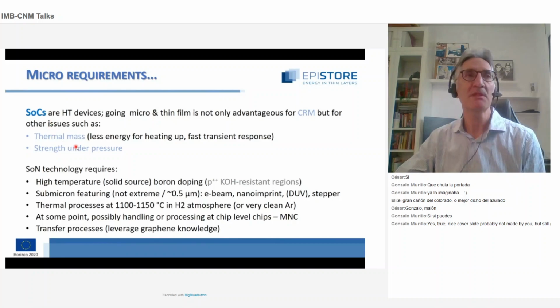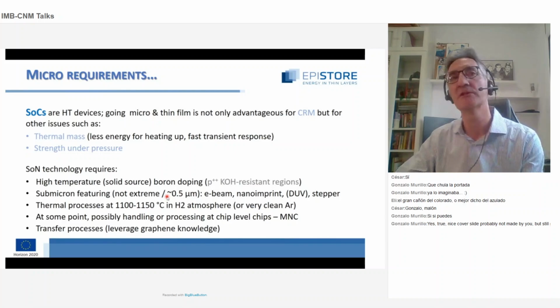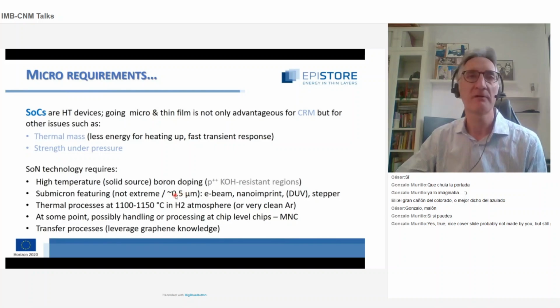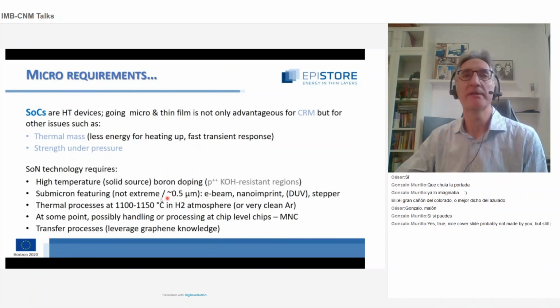Okay. And from a technology point of view, the things that we need to deal with at the clean room level for developing these sorts of devices are high-temperature boron doping. Usually we do this with solid sources because we need to define some P++ KOH-resistant regions. We need, as I explained to you, some submicron features, but not really extreme. The diameter and pitch of the holes that we need to produce in the silicon can be around half a micron. So this can be attempted by e-beam, nanoimprint, DUV, if we end up having one, but even with the stepper, it's at the limit of the stepper.